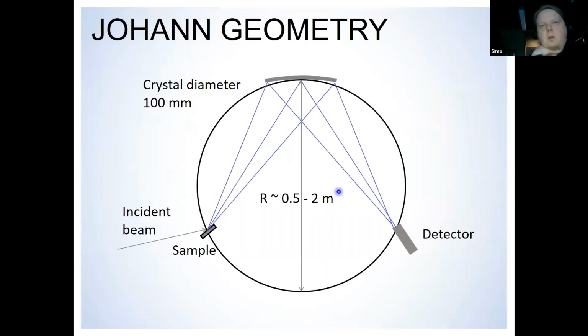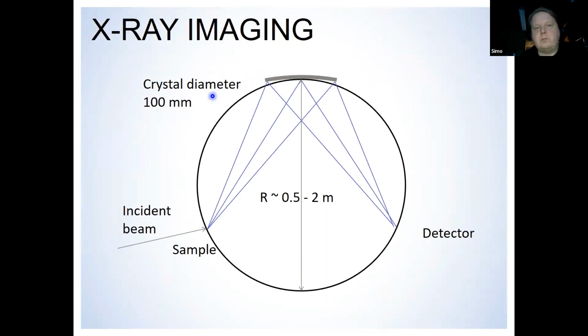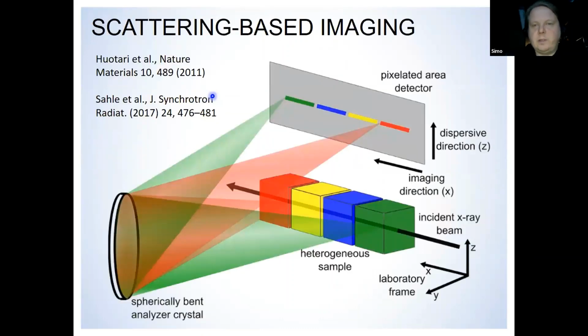All right. So imaging: why and how we could do imaging with this. This is the Johann geometry. We have a spherically bent crystal analyzer arranged in a Rowland circle where the sample, detector, and the crystal are all aligned. And then we started to think that if the sample has some heterogeneous nature, it of course will get imaged onto a detector if we have a position sensitive detector, because this crystal at the same time acts as a mirror. It's a focusing monochromator, right? So this turned out to be real.